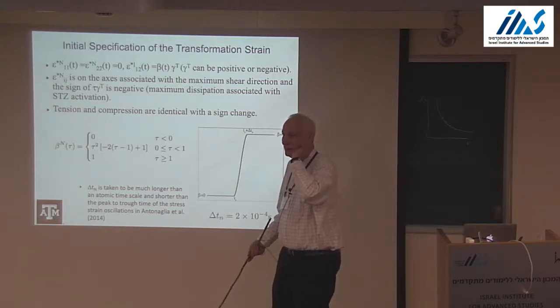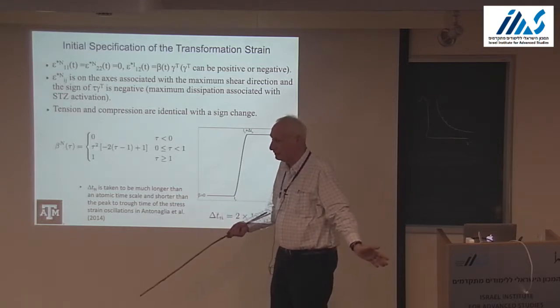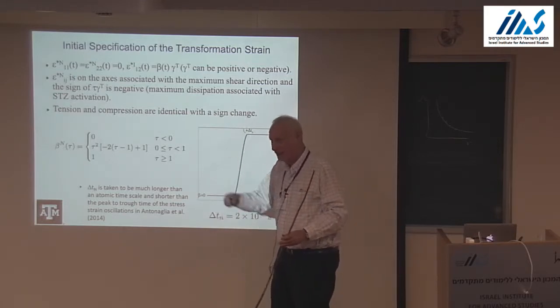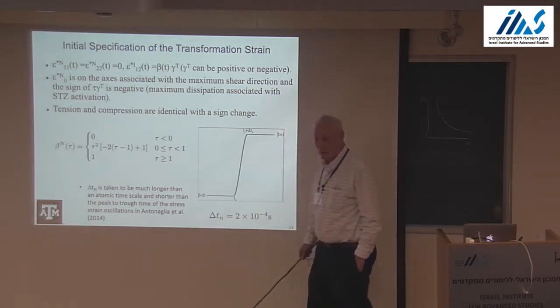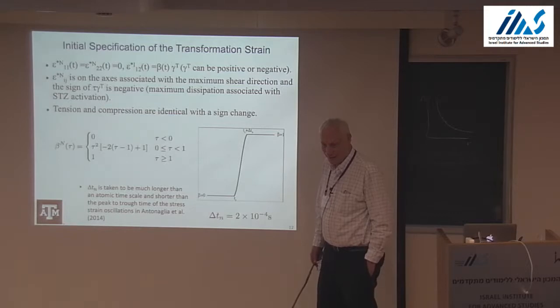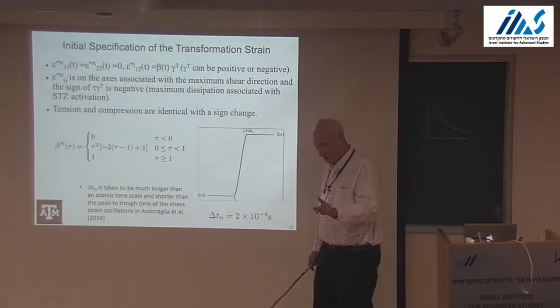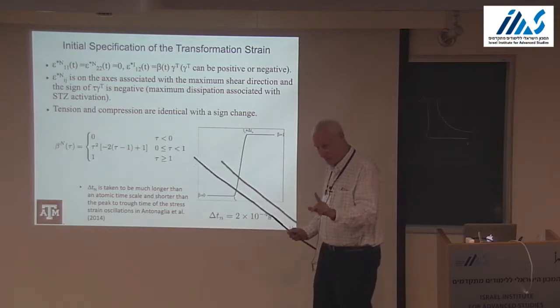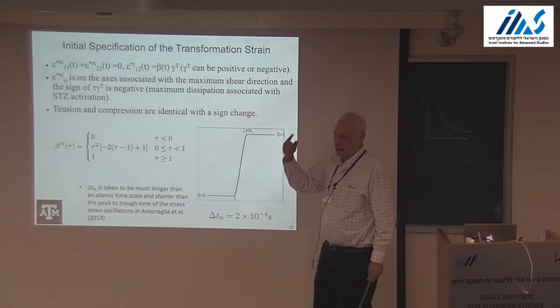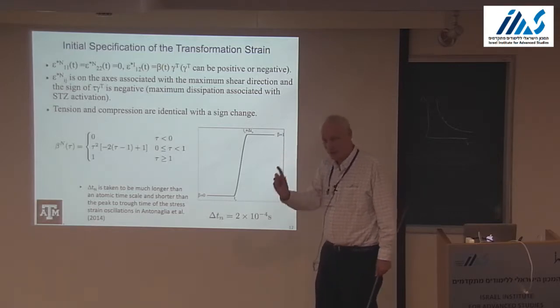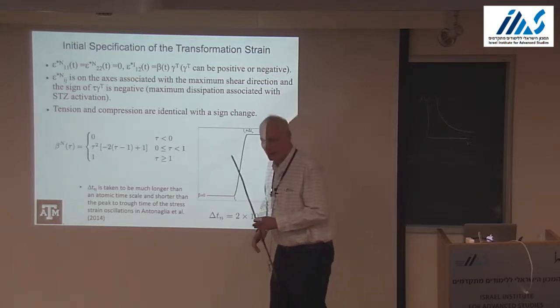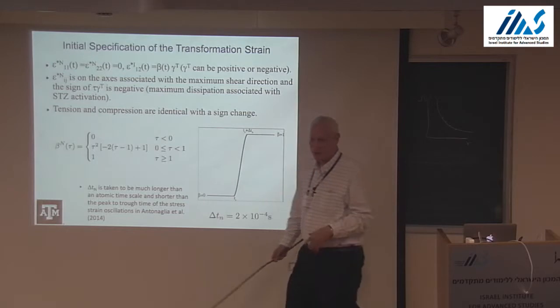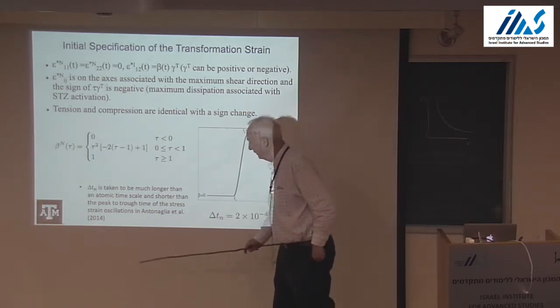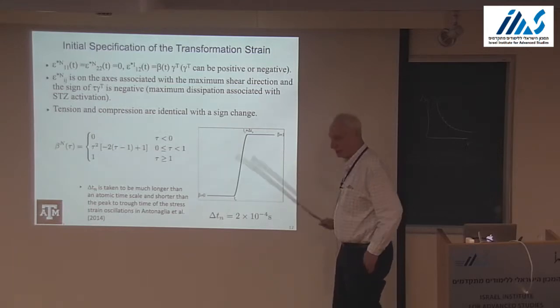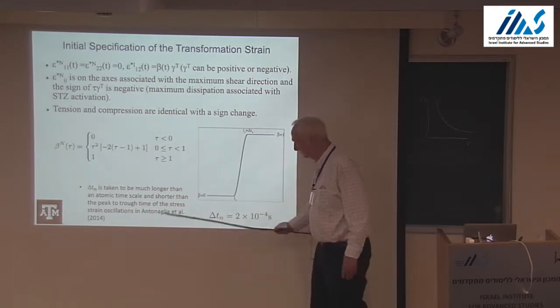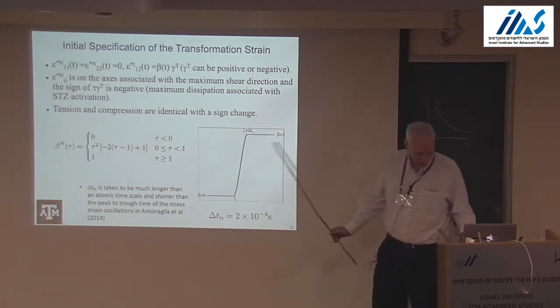Are the sites pre-chosen, or do you... No, the site is fixed. The sites are pre-chosen here. Again, that's a limitation. One expects they would be changed as... As they deform, do you reassign a random threshold? What we do is, I'll explain later, there's a threshold, and then we say you need some relaxation before it can activate again. So we do a delay time before it can be activated. But it's the same threshold. Same threshold. Again, that can be changed. But what we try to do is just take the initial thing. Also have some initial time for the transformation to take place. So we take it to be much larger than an atomistic time.